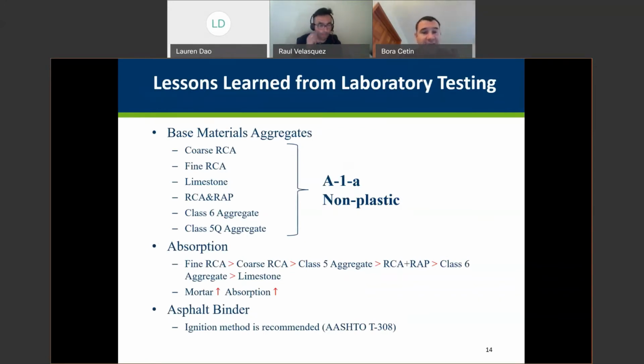And overall, what we learned from laboratory testing: based on the AASHTO soil classification system, all our materials are A-1-a materials, which are good quality and appropriate materials to be used as base materials. All of them were non-plastic. But one important characteristic is that higher absorption is expected because of the leftover cement content. RCA materials, recycled concrete aggregate materials, had higher absorption, and this is related to the mortar content, as we put in the second line item there. The higher the mortar content, the higher the absorption value your RCA will have.